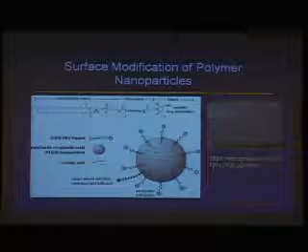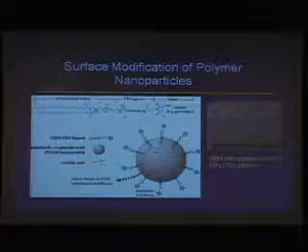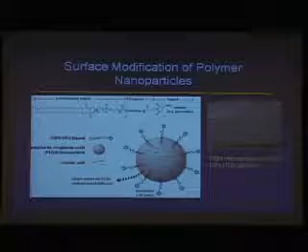And Chris Cheng, who's a PhD student now in MBMB, has developed different approaches. You might be asking if there's a problem with having particles that have high amounts of avidin, of foreign protein, on the surface. Avidin is used in pharmaceutical preparations. We don't think that's particularly a problem, but you can avoid the avidin altogether if you want by taking the molecule of interest, and here is the example showing a peptide, and coupling it through a fairly common conjugation chemistry to a phospholipid, DSPE.